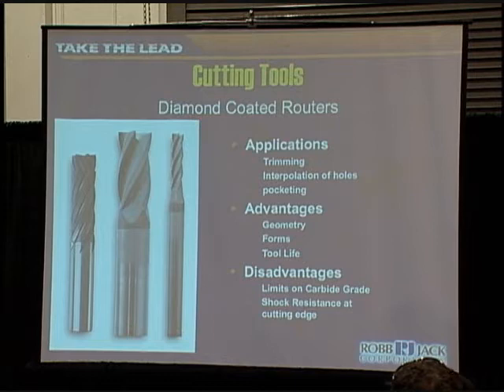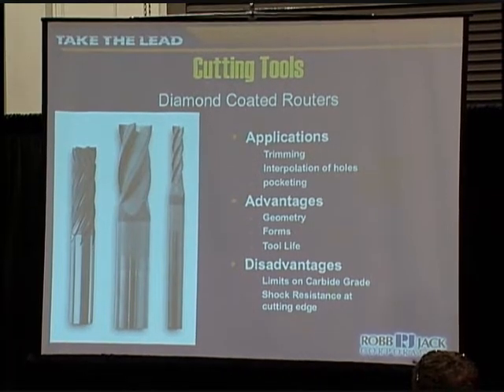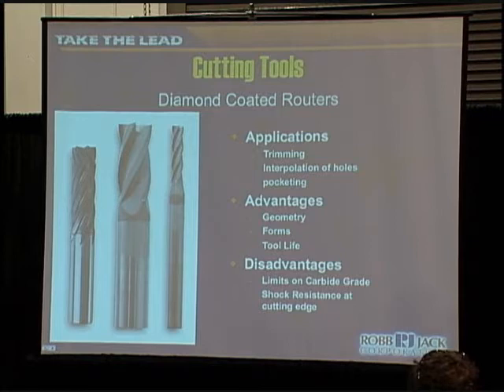The diamond coated routers typically aren't used as much as the PCD routers or the carbide, but if you have a part where you don't have chipping problems or things like that, you can use a diamond coated router. And you can see this variation here: we're able to put an up shear and a down shear on the tool so that it puts positive pressure on the top edge and positive pressure on the bottom edge at the same time. So it kind of squeezes the material into itself so you don't get delamination.